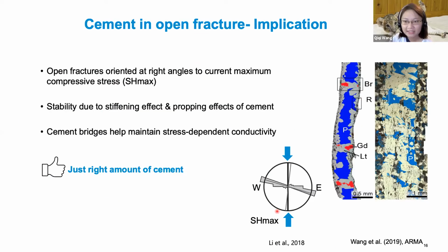And what is interesting is that these fractures I studied are striking east-west. They are perpendicular to the current maximum horizontal stress. So normally we would expect fractures of such orientation to be closed due to the maximum horizontal stress orientation, but they remain open. We would like to know why. Our hypothesis is the cement bridges we study. Right, I'm showing examples here. The cement bridges go from one fracture wall to the other, and they can hold the fracture open under unfavorable stress conditions. So with that, we believe with just the right amount of cement, the fracture cements can help maintain stress-dependent conductivity during reservoir depletion. Also, I want to mention the extensive cement in the rock mass, in the host rock, will make the matrix rock stiffer, and that will help retain the fracture open as well.